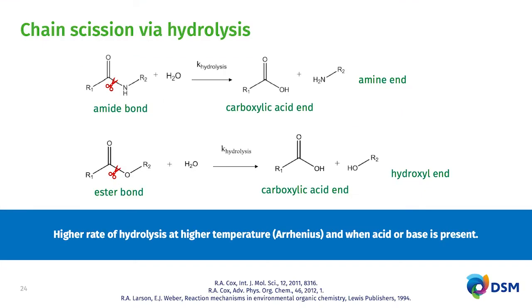The second example shows the same thing. The ester bond from polyester reacts with water, and water starts to cleave the ester bonds, such that we start to have more and more carboxylic acid end groups and hydroxyl end groups being created as a result of hydrolysis. The hydrolysis rate typically is higher at higher temperature, following Arrhenius behavior, and when acid or base is present. So it can be acid-catalyzed or base-catalyzed hydrolysis for amide and ester bonds. This is very popular, and a lot of people know about this.